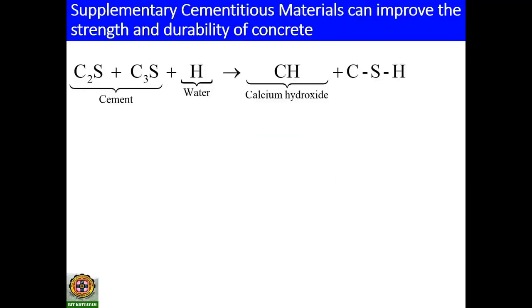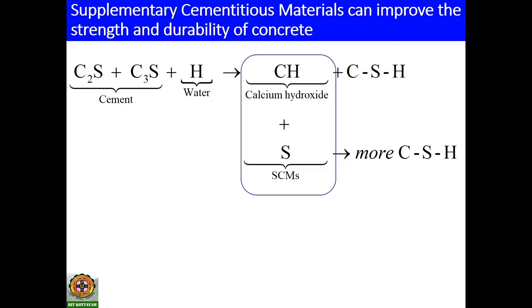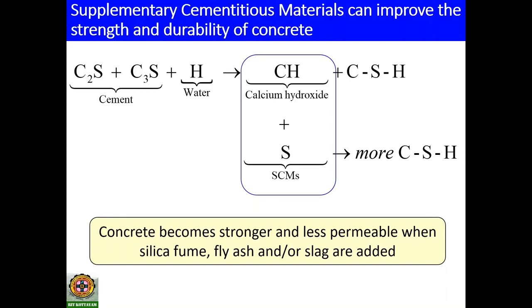Then, supplementary cementitious materials can improve both strength and durability. This we already discussed. Supplementary cementitious materials have reactive silica, so this supplementary reaction, the pozzolanic reaction, will end up with more CSH, and because of the production of more CSH, we will have more strength as well as a less permeable system developed.